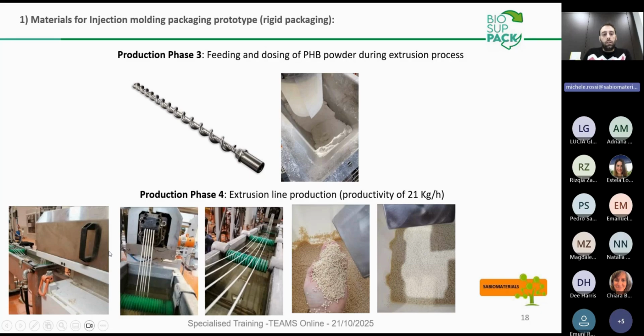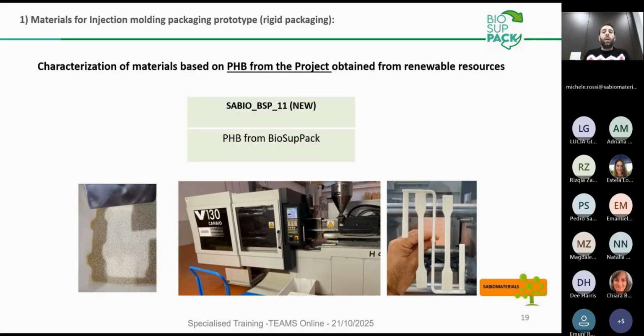In this case, you can see that the material goes out from the extruder, a twin screw extruder that presents 5 filaments, goes into a bath of water, and at the end is cut in the air for the formation of the pellet as a final form. The productivity is around 21 kilos per hour. This is our pilot scale that permits to work for several hours. And at the end, we have obtained also in this case 25 kilos, but by using the same formulation developed before, but changing only the source of PHB.